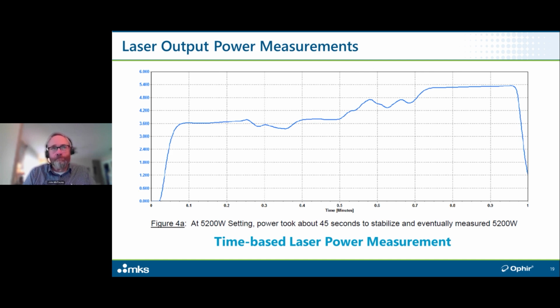Also, beam profile. If we talked about focus shift and what focus shift is doing, that's really not going to be reflected in either way in your laser power. So whether it's a pulse to power or a water cooled system, if you do have focus shift on your system, that's not going to be reflected in the laser power. So you may get a nice stable laser system, but still have problems with your laser. If that's the case, it may be a focus shift issue, may be some kind of component issue. But hopefully that answers that question.